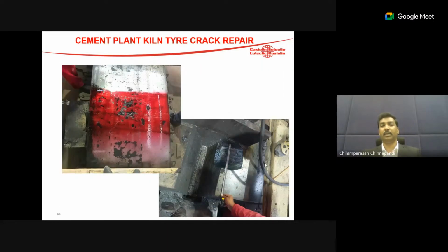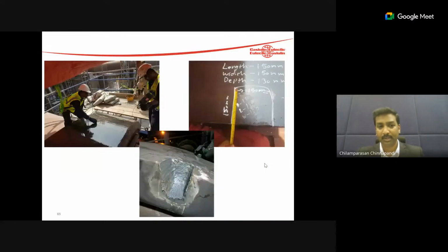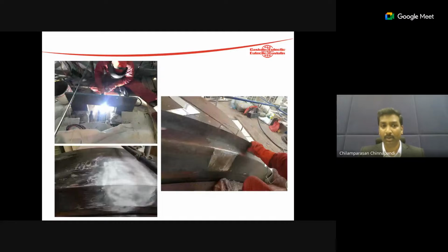This is one of the very specialized applications we have done globally, and for almost 40 years we have been the masters of crack repairs globally. You can see the depth of the crack, and we have checked the depth. It is almost 130 mm, and the length is almost 150 only, but we have done up to 1 meter also. We have gouged out until it reaches the base where there are no further cracks. Our team will work day and night, and we'll keep the interpass temperature readily available, and we'll do the complete rebuilding and grinding to the shape as per the rolling.